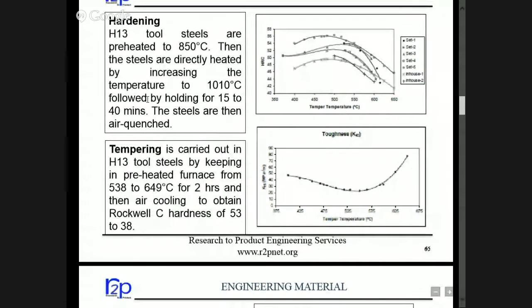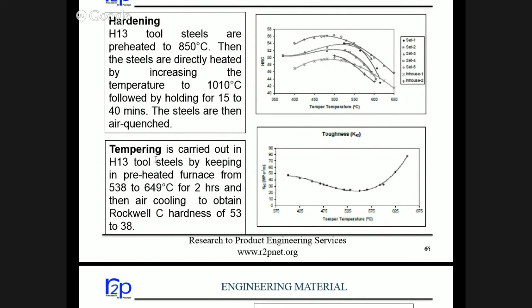And after the die has been made, we need to do the heat treatment, right? So hardening and tempering, because life will only come by that. Otherwise, the number of pieces taken out from a forging will not be that much. We need to have the toughness also. So we need to harden and temper also. And hardening, first we need to harden. So it is heated to 850 degrees centigrade. Then taken to around 1000 degrees centigrade and held there for some time so that the temperature is uniform throughout, and then air quenched.